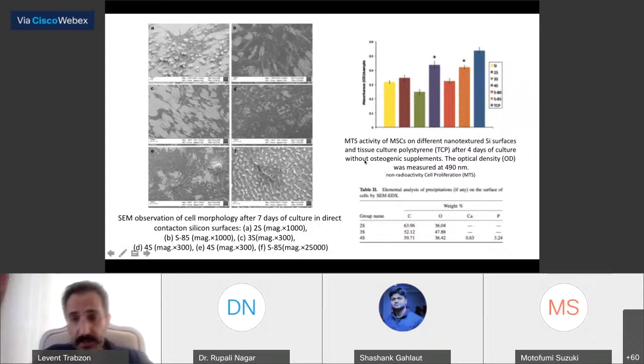That will also be seen in the non-radioactivity cell proliferation experiments on the right-hand side, and you can see clearly over here. The yellow one is the bare silicon, no nanostructures. In some nanostructures, as you see, there is not much difference, even less proliferation, I mean the cell activity. But in some cases, as you see over here in the forest, meaning the square-like cross-sectional GLAD films, that would be very similar to almost the TCP value. TCP is the tissue culture polystyrene.